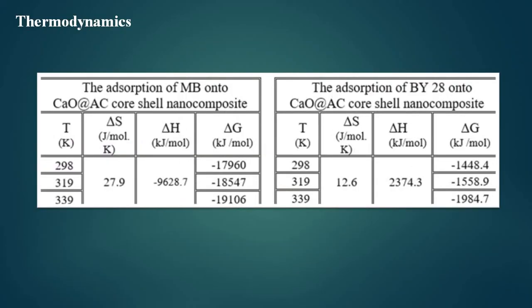With respect to the thermodynamics, we found that delta S has a positive value, indicating more entropy. In the case of methylene blue, delta H has a negative value, indicating the adsorption process is exothermic, and delta G has a negative value, so it is a spontaneous reaction. In the case of BY, delta S has a positive value, so more entropy, delta H is positive, an endothermic reaction, and the reaction is spontaneous according to the delta G value.